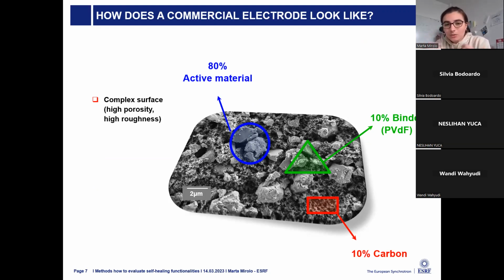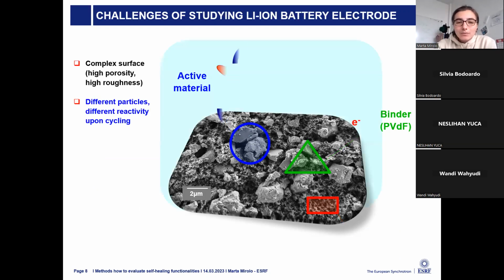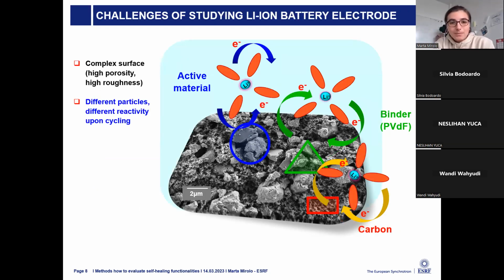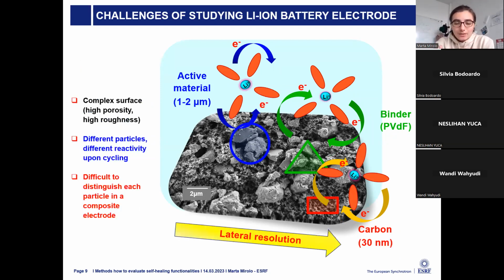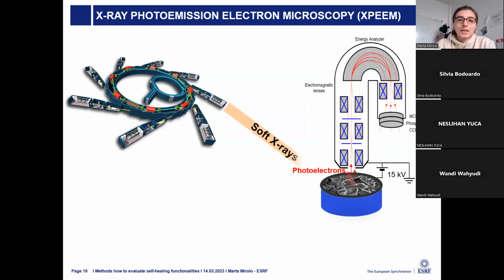We have some conductive carbon to improve the conductivity of the electrode. We have the binder. We already heard earlier on why the binder is so important in electrodes. And when we insert this electrode into a real operating battery, what happens is that when it's in contact with the electrolyte, we can have different reactivity of the electrolyte with the different components of the electrode. And if we want to understand what's going on at each of these particles, we need a technique which provides us chemical information and which has a good lateral resolution, so that we can distinguish really the different particles.